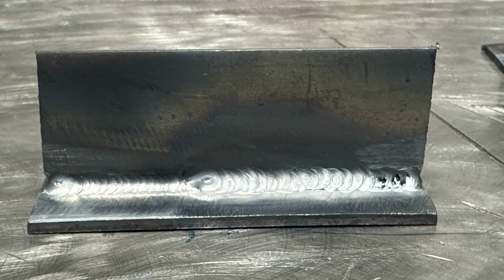This is a weld that you just saw happen, and you can see that even though in the video it didn't look like I was wandering that much, a correct TIG weld is on the left of that, and just that little bit of wandering chewed away higher and lower on that plate, and that's undesirable. That weld is going to be more or less very concave, very little throat depth, and it just doesn't look that good. So by keeping a tighter arc, focusing it on the dead center of that root where the plates intersect, will produce a weld like the left third rather than what's on the right.